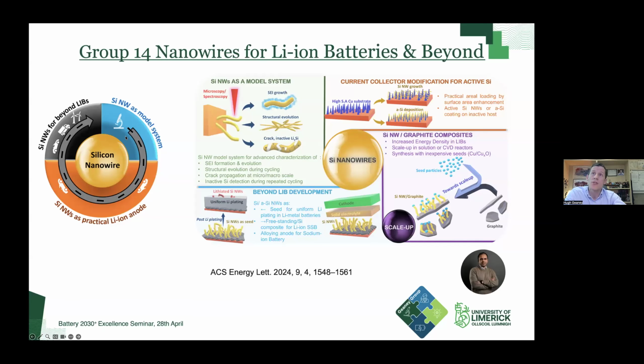I'll show some nice broader examples from the University of Limerick around the model system and the practical side of things. Why they're so interesting as a model system, silicon nanowires specifically, is you can use them very easily to track things like SEI composition. So you can look, for example, at the structural evolution of your silicon active material as it's cycling. And one of the reasons for that is you can very easily grow these silicon nanowires directly from a current collector. So what that does is it removes the impact of any binders or conductive additives. So essentially what you're seeing in that is just the silicon itself. So as I showed in that example previously for germanium, you can track the morphological evolution of the materials as they cycle. On the practical side of things, there have been a number of different approaches to try and modify these silicon nanowire systems for practical applications.